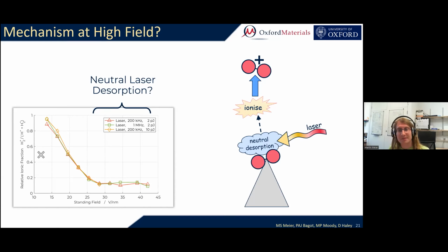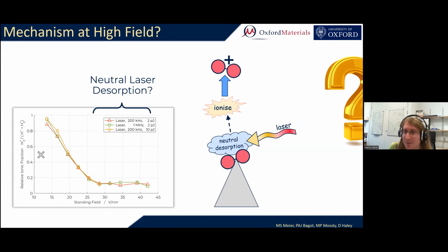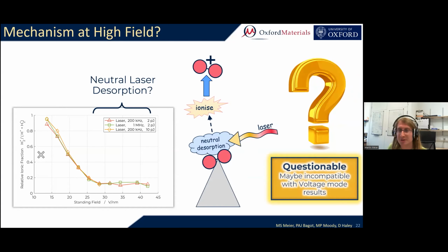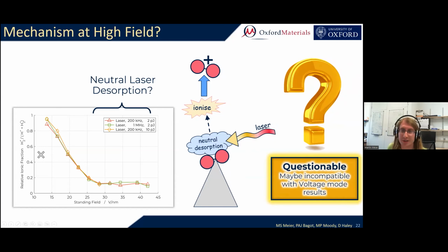In voltage mode, we have seen that at high electric fields, A, there is no hydrogen left at the tip, or B, all of the hydrogen is evaporating off pulse. So the question is this: in the first place, how would it be possible for an H2 to sit on this tip here in laser mode, and why does it not immediately fly away in the standing field? It would still be possible that maybe the laser is also doing something to supply a lot of hydrogen onto the tip, but it definitely is a point of concern. It's raising a major question mark above the model, and it's something that we would need to explain first if we would believe that this is what's going on in the tip.